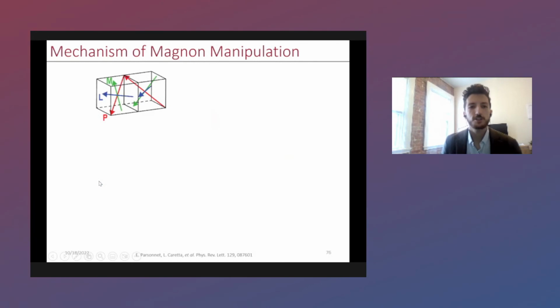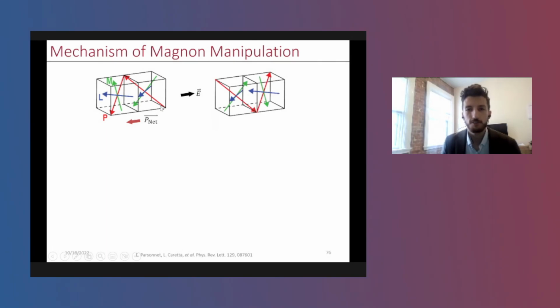So why is this actually happening? Well, I can explain this very simply by using this right-hand rule that we know about in bismuth ferrite. It's quite complicated, so I'll walk you through this arrow by arrow. As you can see in this configuration, the polarization, red arrows, have a net polarization to the left. And of course, I've explained that if you apply an electric field, you can orient the polarization in the opposite direction.